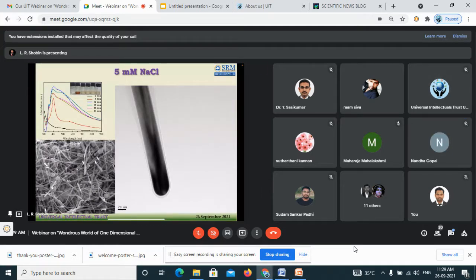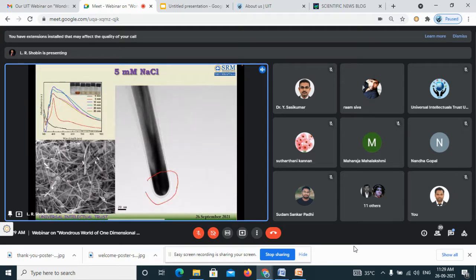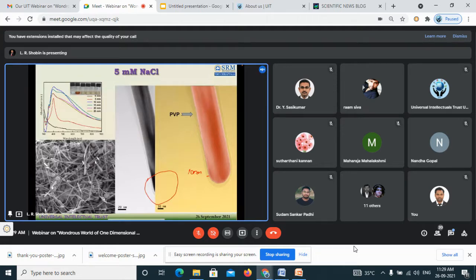Okay. So I'm further increasing the salt concentration, going from 2.5 to 5 millimolar. I'm able to get linear wires compared to the previous system. Here I'm getting very linear wires, but these are all capped with polyvinyl pyrrolidone, which we use as a capping agent. We found around 10 nanometer thickness of PVP coating over these silver nanowires. This is a negative, because this 10 nanometer thick PVP is insulating in nature.